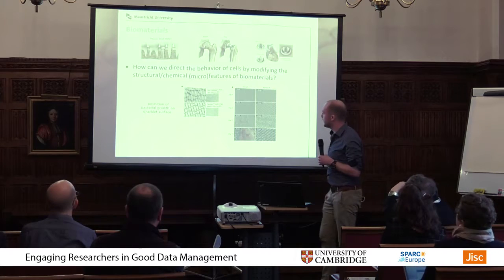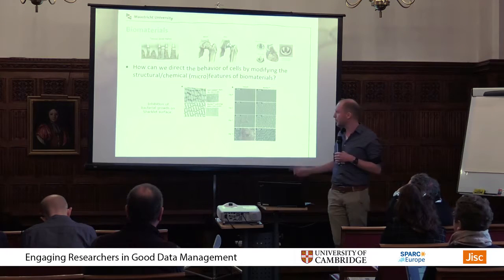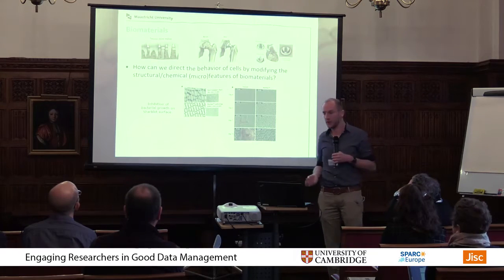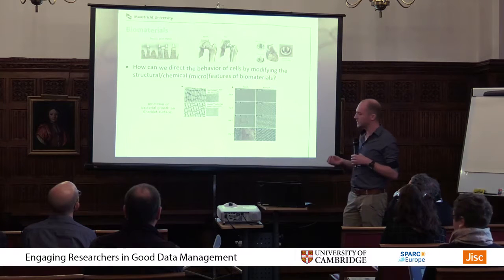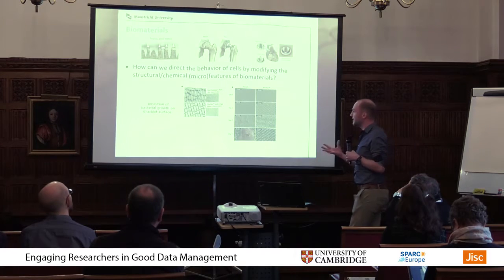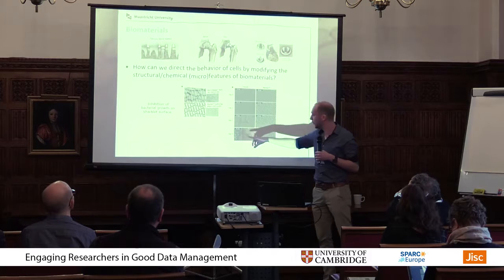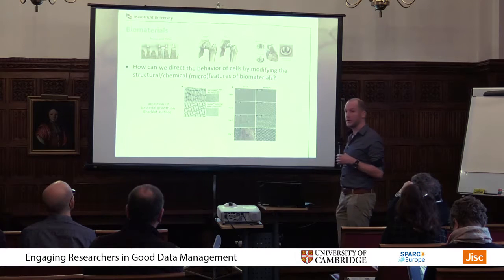A really nice example: a research group in the States took some skin of the Galapagos shark, which has a very specific surface structure on its upper layer. They copied this into a plastic material, the exact same shape as the shark skin. They did this because this shark skin is very sterile — no bacteria attach to it. After copying it into plastic and introducing bacteria on these surfaces, after two weeks the smooth standard plastic surface was completely covered, while the artificial shark surface had almost no bacteria on it at all.